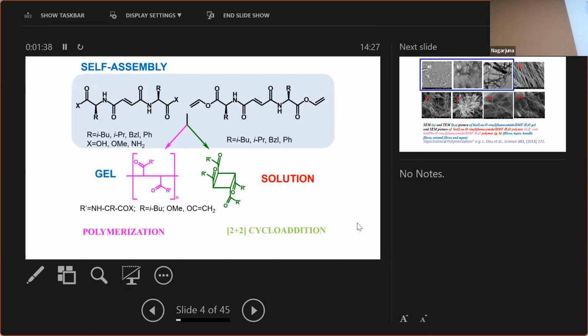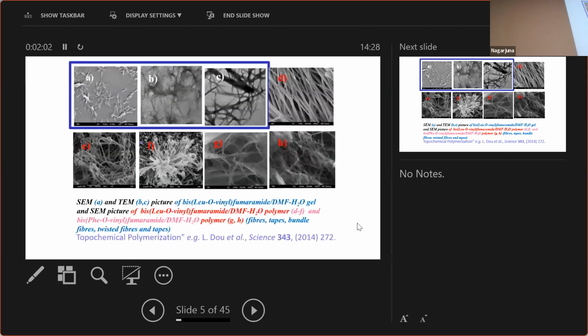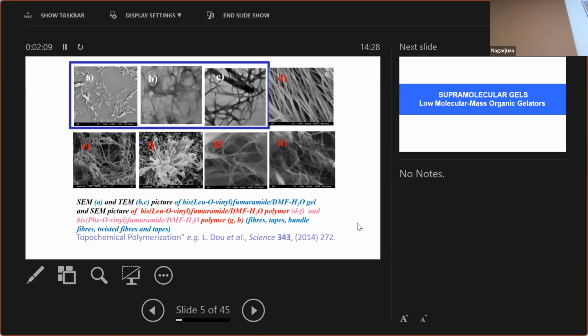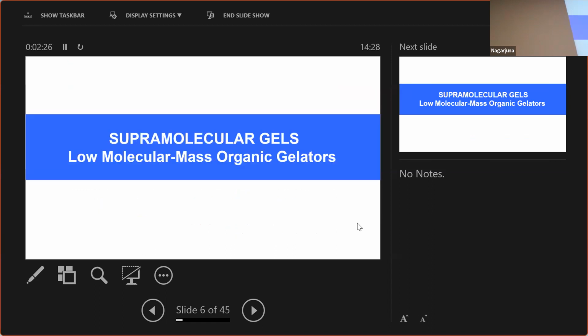If you do photochemistry on polymerization solution, usually we will obtain [2+2] cycloaddition. But if polymerization occurs in a gel or in self-assembly, we should obtain polymers. Actually, here is some micrography and SEM micrography of starting gel materials in a mixture of DMF and water. And another is the same picture of the obtained gel. But I'll start from the beginning.